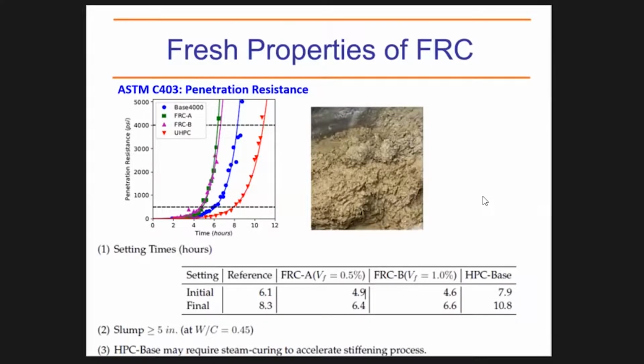So the target slump was 5 inches, which was good. We achieved a good workability even after adding the fibers, so we don't lose much of the setting times. According to ASTM C403, we did the penetration resistance test to look at the setting times. With the references, when we compare them, there is not much difference.